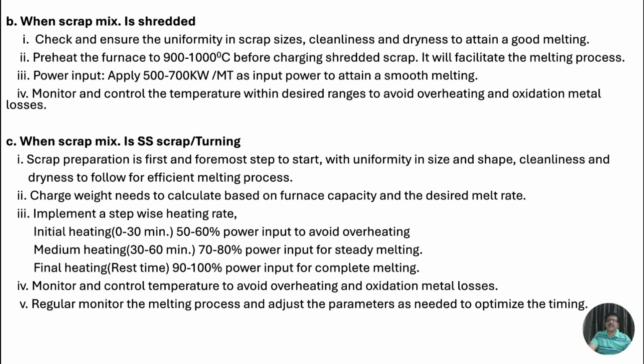When the scrap mix is SS scrap or turnings: Number one, scrap preparation is the first and foremost step to start with, with uniformity in size and shape, cleanliness and dryness to follow for an efficient melting process. Number two, charge weight needs to be calculated based on furnace capacity and the desired melt rate. Number three, implement a stepwise heating rate. Initial heating, 0 to 30 minutes, 50 to 60% power input to avoid overheating. Medium heating, 30 to 60 minutes, 70 to 80% power input for steady melting. Final heating, rest of the time, 90 to 100% power input for complete melting. Number four, monitor and control temperature to avoid overheating and oxidation metal losses. Number five, regularly monitor the melting process and adjust the parameters as needed to optimize the timing.